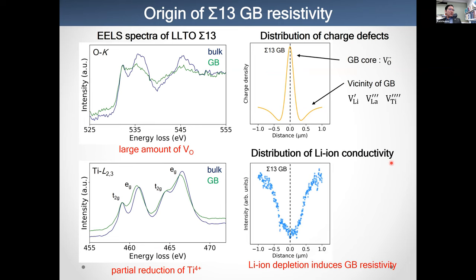So this is again the conductivity of the grain boundaries I showed you. In this case, conductivity is reduced like that. Then lithium vacancy is increased, and therefore the lithium ion concentration must be reduced, and therefore lithium ion conductivity is reduced. So the lithium ion depletion induces the grain boundary resistivity.